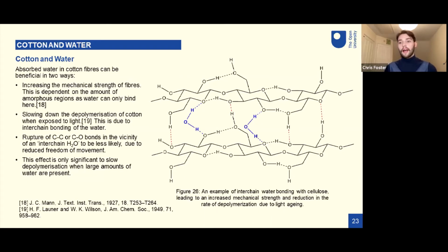Cotton and water show an interesting relationship. When water is absorbed into cotton fibres, it can actually be beneficial in two ways. The first of these is water will actually increase the mechanical strength of fibres. This is, I should mention, dependent on the amount of amorphous, so that disordered region there is within the fibre, because water will enter the pores and it can bind in these amorphous regions, as shown in figure 26.